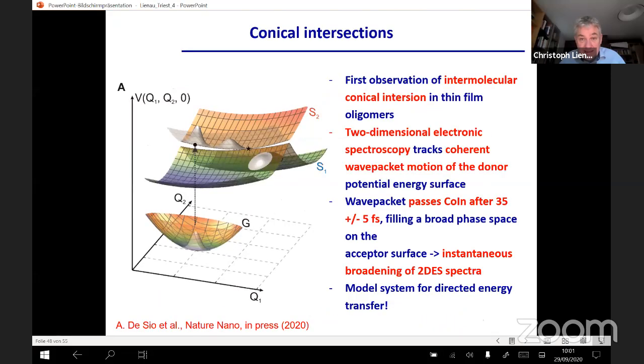So with this, it's time to conclude. In this last part, we have seen a very peculiar result of electron-nuclear coupling. It's not just promoting charge transfer, but it's also driving relaxation processes in a directed manner between optically bright and optically dark potential energy surfaces. And that is what we have seen in the form of this intermolecular conical intersection that we've studied here in